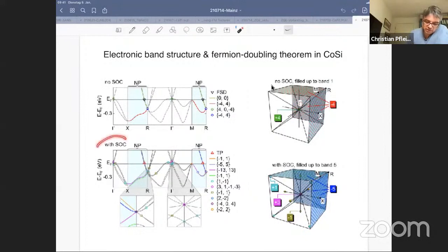If you take spin-orbit coupling into account, the situation becomes more complicated, right? So you have charge at the gamma point, but then you also have charges close to the R point and the M point, right? And including then the charges, this is now considering filling up to band 5, you find that actually there's a network of topological charges and they're all connected up.